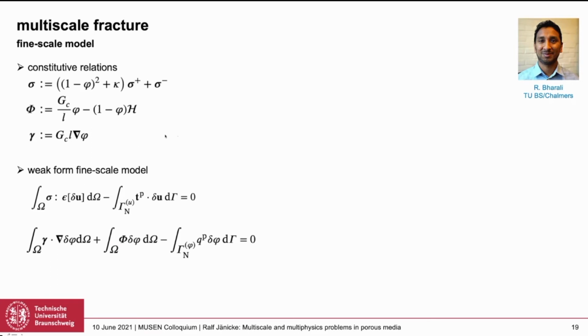I would like to see how such a formulation can be introduced on two scales, how this can be interpreted on two scales. And it is not obvious that this is possible, because even though we have here a smeared damage model, damage in a fracture propagation is still a localization of a property. So we have still a local damage, even though it's smeared out. But compared to the sample size, this is, of course, still local. And it is not that easy or obvious to see how this could work in a concept where we have an RVE on a small scale. So that's what we wanted to find out.